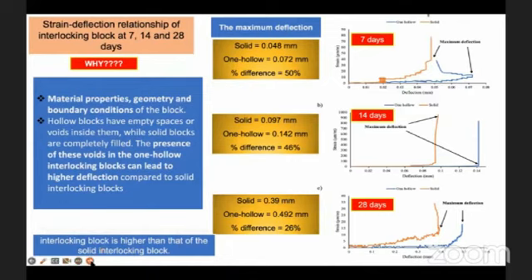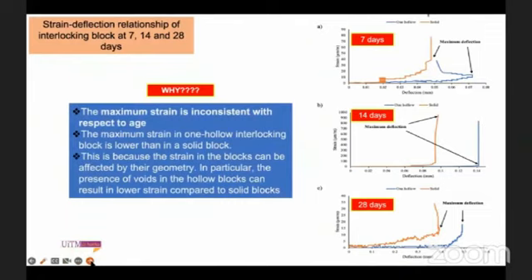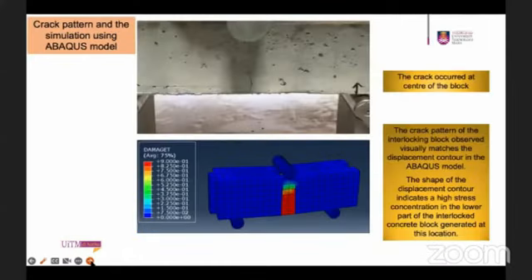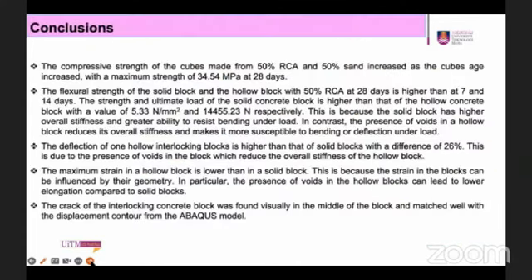Okay, this one is the result for the strain deflection relationship of interlocking block at 7, 14, and 28 days. We found that the maximum strain is inconsistent with respect to age, and the maximum strain in the hollow interlocking block is lower than that in the solid block. And this one, the crack pattern and the simulation using the Abaqus model, where the crack pattern of the interlocking block observed visually matches the displacement contour in the Abaqus model.